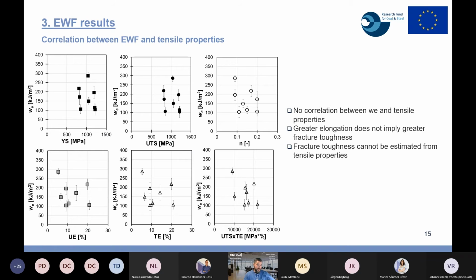Another important message that we wanted to repeat is that crack propagation resistance cannot be estimated from tensile properties. Here we plot the specific essential work of fracture for all the steels investigated, also as a function of different tensile parameters: the strength, the ultimate tensile strength, strain hardening, uniform elongation, total elongation, also the product of the UTS by the total elongation, which is usually also used as a toughness indicator.